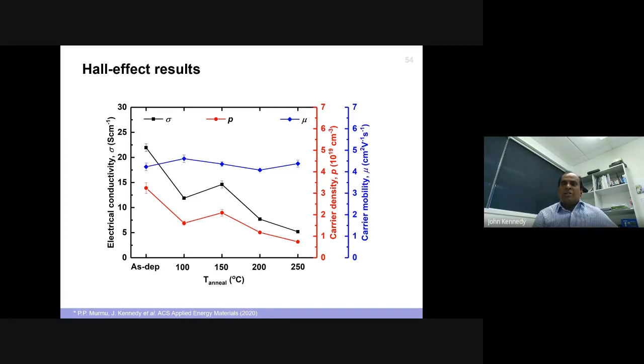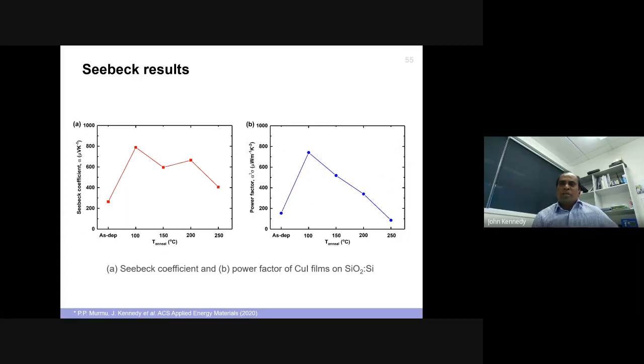research we got on the transparent one. Obviously, Seebeck, it's actually quite good for 50 to 100 degrees, which is the maximum heat you can anticipate in a glass window if you cover them over a large area. So as I said, when you look at the power factor, which is directly related to the efficiency, it was really high, from room temperature, say 50 degrees to 100 degrees C.